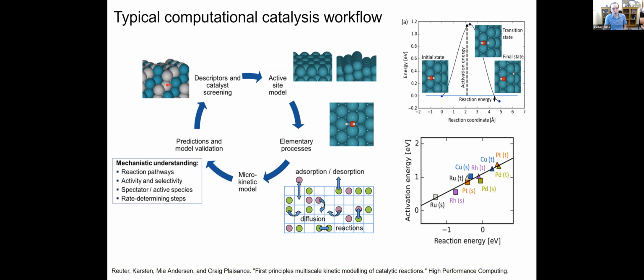Once we have a certain surface or set of surfaces that we think are interesting, we drill down and we start thinking about what are the particular active sites that might be responsible for the activity on a structure like this. We model all of the elementary processes, individual elementary steps for all the reactions that can happen. If we still think it's interesting, we might go to a more complicated microkinetic model, perhaps that has diffusion or some sort of surface lattice. There's a ton of catalysis that considers simultaneously adsorption, desorption equilibrium, along with diffusion, along with reactions on the surface. These all go into a larger microkinetic model that allow us to predict activity and selectivity.